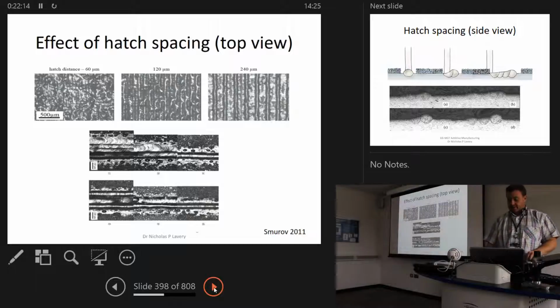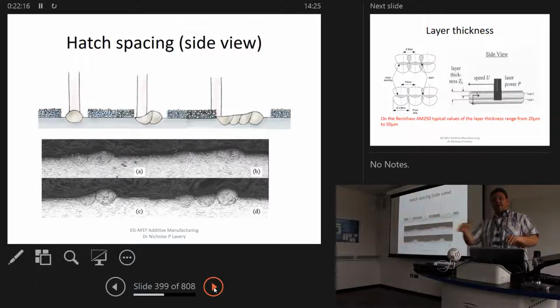And this has implications because the next time the powder comes over, some of those areas now have no powder, so whether you've actually built up a nice even layer of powder, which theoretically you want to do, is not necessarily the case. So if we look at, for example, this sketch at the top by Smurov et al., you can see quite clearly the denudation area there. On the first one, which is a single track, you've just come down the first time, you can see the melt bead's got a very nice shape. That's the sort of thing you always want to have. It's a sort of dome, slightly elliptical underneath. On either side of it, you can see the powder's been blown away.